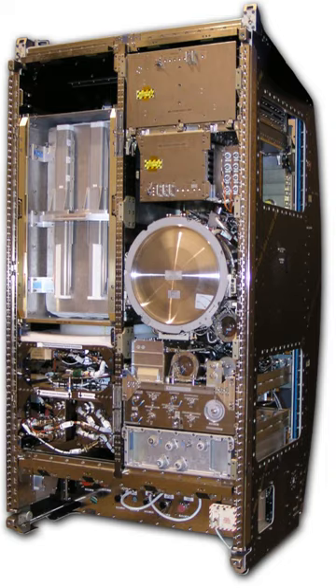The processing chamber provides an accurately controlled processing environment and measurement of microgravity levels. It can house several different furnace inserts. During the first batch of experiments, the low gradient furnace (LGF) is installed. Another furnace, the solidification and quenching furnace (SQF), is already produced and waiting on ground for future operations. The FIS can be moved with a dedicated drive mechanism to process each sample according to requirements from the scientists. Processing normally takes place under vacuum.